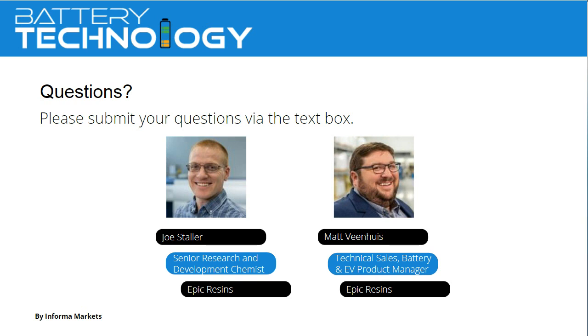Next question. What is recommended for use in LED lighting applications where an optically clear solution is needed, epoxy or urethane? I would tend to lean towards aliphatic urethane material for an optically clear LED solution, mainly because of the UV stability. We've seen a lot of customers who have been offered epoxy systems which are not aliphatic, which can yellow and degrade under UV light quite rapidly. So, like Matt was just saying, we recommend aliphatic urethanes for those applications. They have a lot better longevity over time.